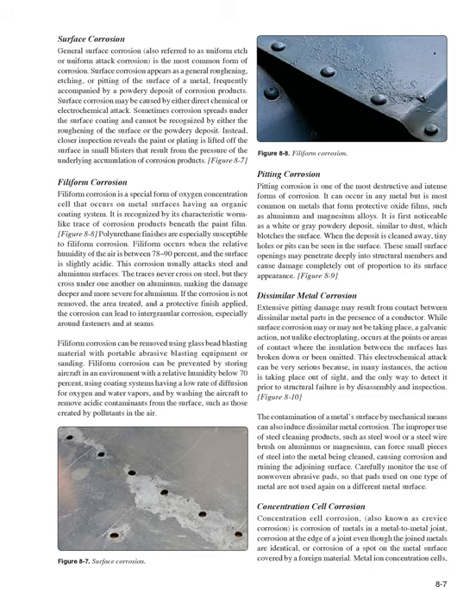Figure 8.10, the contamination of a metal's surface by mechanical means can also induce dissimilar metal corrosion. The improper use of steel cleaning products, such as steel wool or a steel wire brush on aluminum or magnesium, can force small pieces of steel into the metal being cleaned, causing corrosion and ruining the adjoining surface. Carefully monitor the use of non-woven abrasive pads, so that pads used on one type of metal are not used again on a different metal surface.